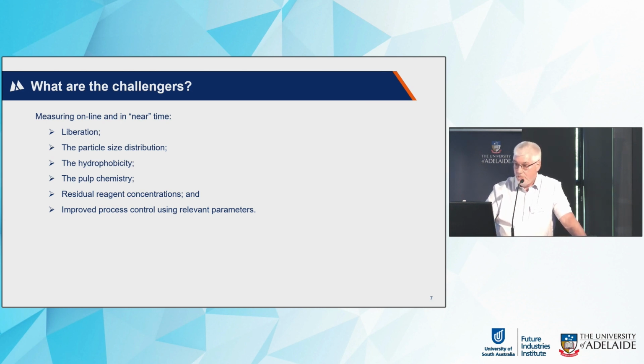Obviously, pulp chemistry, Bill's talked about the Magotteaux pulp. Measuring pulp chemistry is the first step in getting to some of that hydrophobicity numbers and trying to improve the flotation process. If we could measure residual reagents in the pulp, collector, frother, perhaps we can adjust those reagents so that we can reduce the amount we're adding and be more efficient. If we can measure all these things, it then means that we can actually improve the process control because we're actually starting to measure the critical parameters that drive flotation.